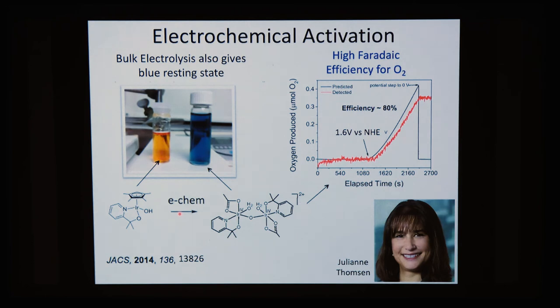Julie preferred a different structure, as you can see here, because we're not certain of the exact nature of the ligands, apart from the pyalk iridium oxygen iridium pyalk unit. And this has a reasonably high Faradaic efficiency for oxygen, but because we are simultaneously burning off the Cp*, the difference between the current passed and the oxygen that is evolved is probably due to burning the organics to become carbon dioxide and acetic acid, of course.